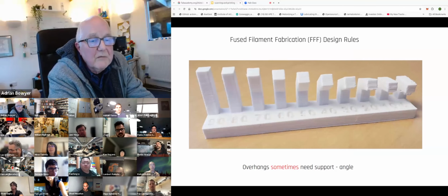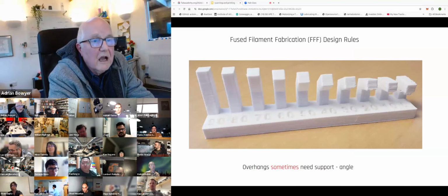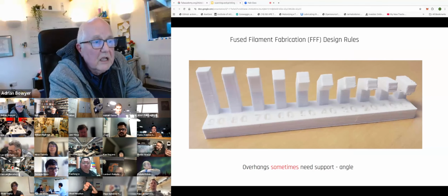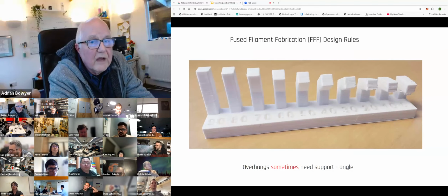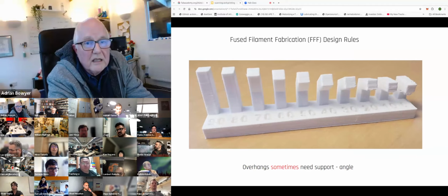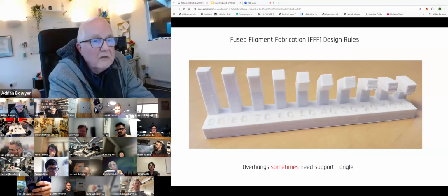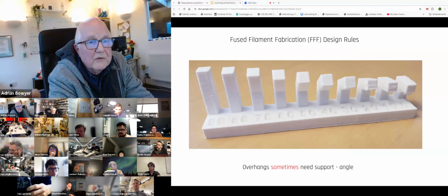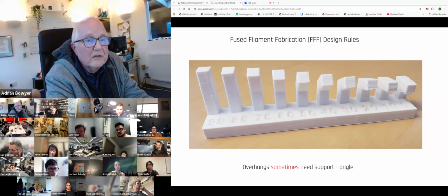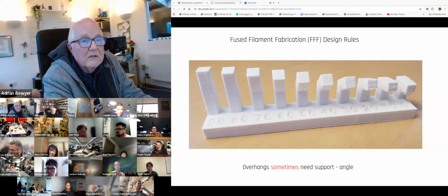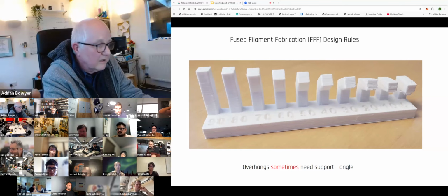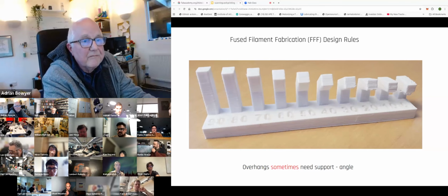Okay, now I say we need to support things that overhang. In fact, we don't, as long as the overhang is not too bad. And here's an experiment with a whole series of different angles of overhang. You can see at the extreme right-hand end, we've got a very poor print, particularly on the underside of the overhang. But down to about 40, 30 degrees or so, the print is pretty good. So this technology can allow us to do a certain amount of overhang as long as it doesn't get too flat an angle. And that's something that's quite advantageous.